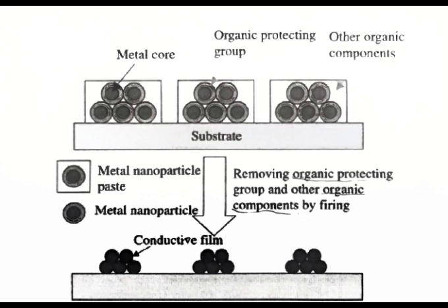Oh, okay. And one of those altered properties is the temperature at which those organic protecting groups and the other organic components in the paste will actually decompose and basically vaporize. Oh, interesting. So you can actually remove them and fuse those metal nanoparticles together into a conductive film at temperatures below 300 degrees Celsius, which is a huge difference from that over 550 degrees Celsius that we're talking about for those traditional thick film pastes. Okay, so that lower temperature, I mean, that really opens up a whole world of possibility. Suddenly you can use these pastes on plastic substrates. And now we're talking flexible displays, bendable electronics, wearable technology, right?